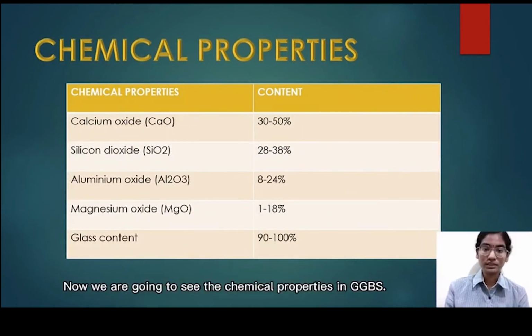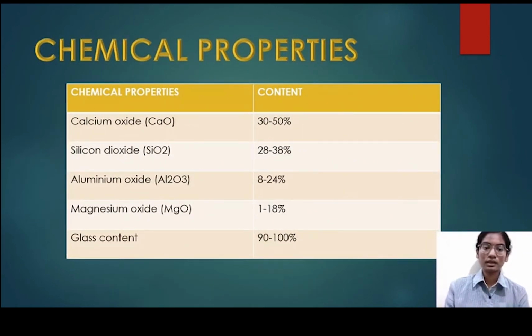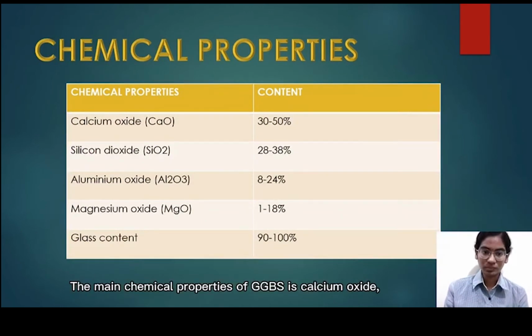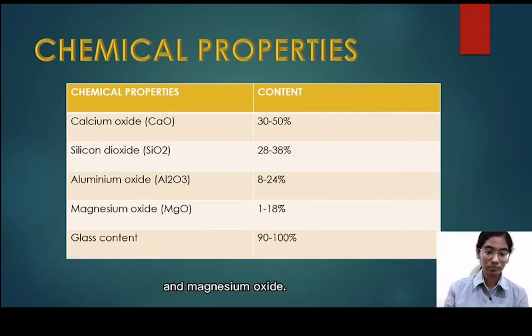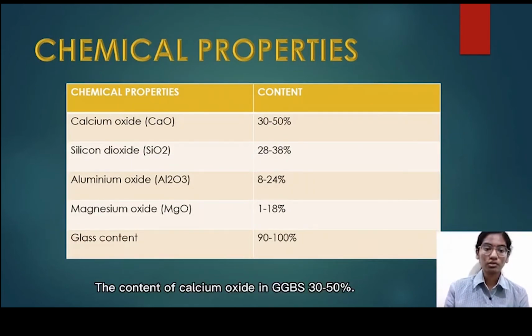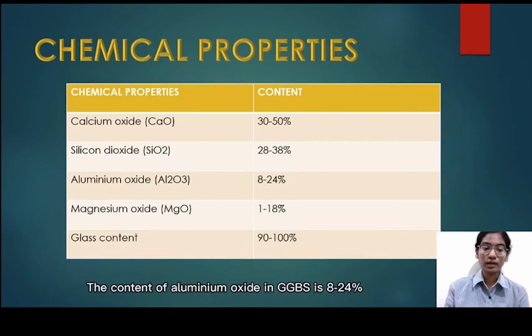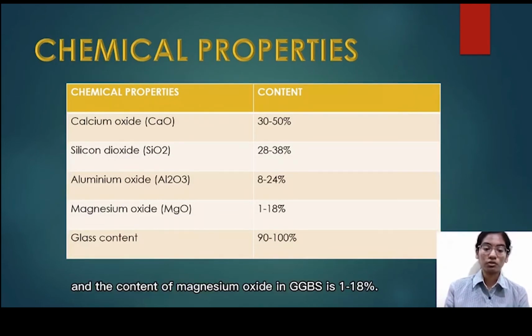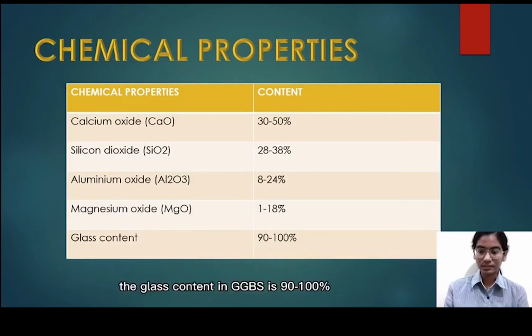Now we are going to see the chemical properties in GGBS. The main chemical components of GGBS are calcium oxide, silicon dioxide, aluminium oxide and magnesium oxide. The content of calcium oxide in GGBS is 30 to 50%. The content of silicon dioxide in GGBS is 28 to 38%. The content of aluminium oxide in GGBS is 8 to 24%. And the content of magnesium oxide in GGBS is 1 to 18%. And lastly, the glass content in GGBS is 90 to 100%.